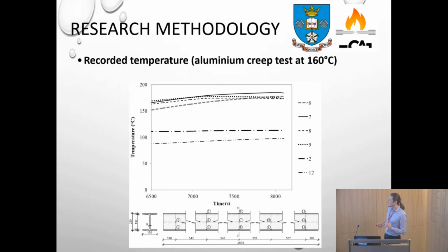When it comes to aluminium, it's also good, but the aluminium is not ferromagnetic, so we can get better heating of the specimen inside if the specimen is ferromagnetic. If it's not, then the temperature dispersion is a bit higher. In case of aluminium, we have slightly higher dispersion of the temperatures when we did the tests. Both the aluminium column and the steel columns had the same length when we did the tests.